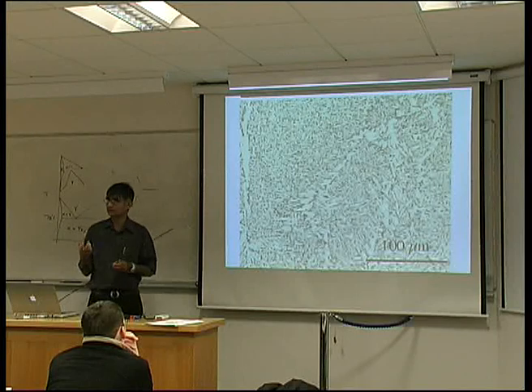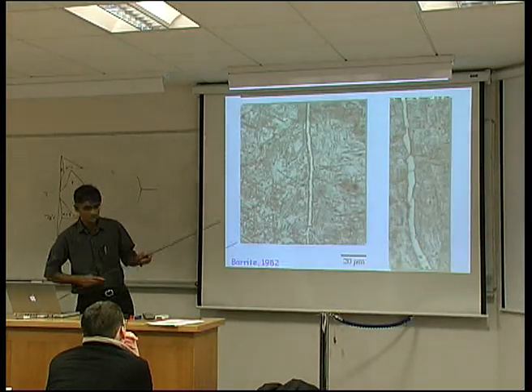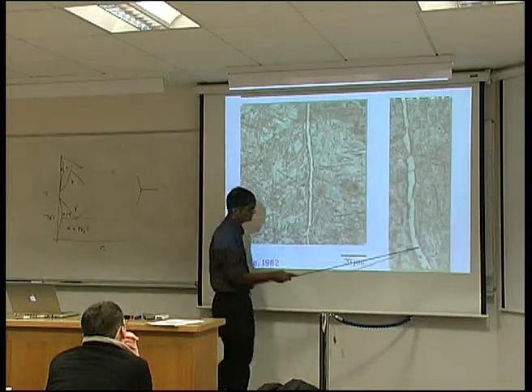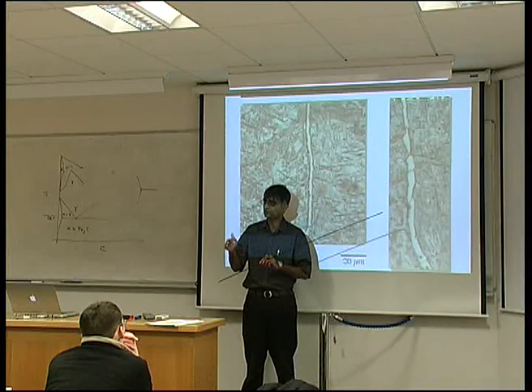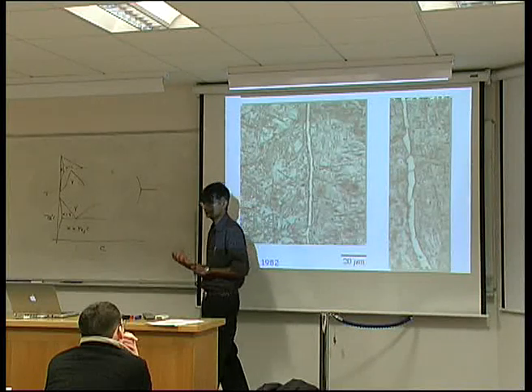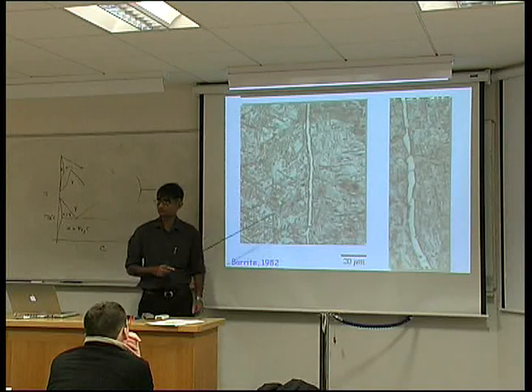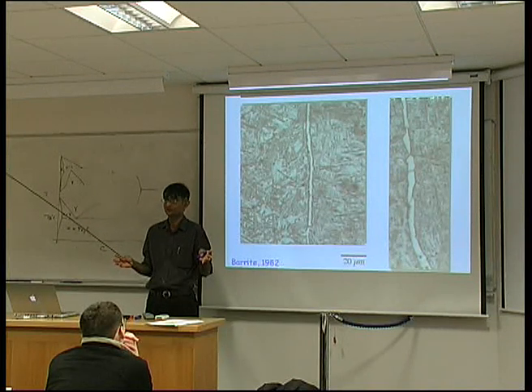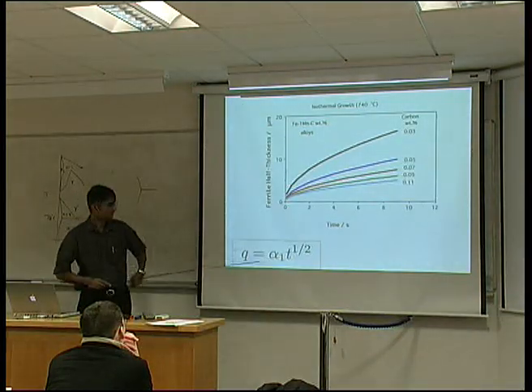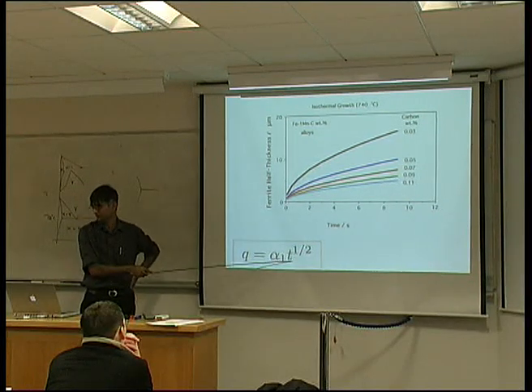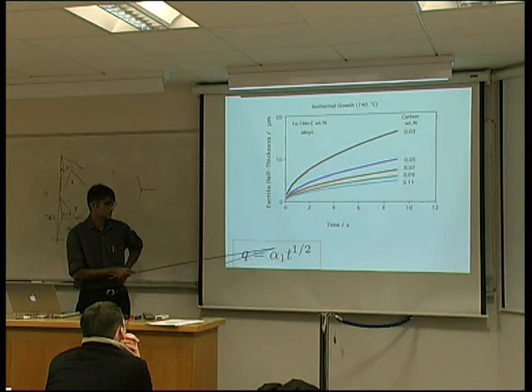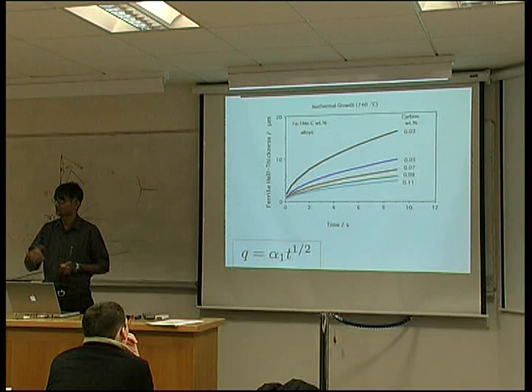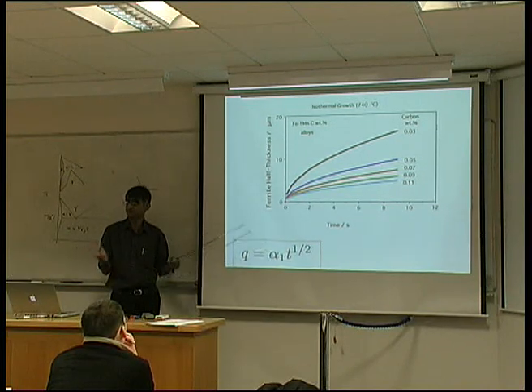Here is a real micrograph of the weld metal microstructure. You can see layers of allotriomorphic ferrite along the austenite grain boundaries, plates of Widmanstätten ferrite, and intragranularly nucleated bainite — what we call acicular ferrite in the welding industry. These layers of allotriomorphic ferrite are bad for properties because they don't contain much microstructure; a cleavage crack can simply propagate without deflection across that grain. It's very convenient that they completely decorate the boundary, because we can treat the growth process as one-dimensional diffusion-controlled growth.